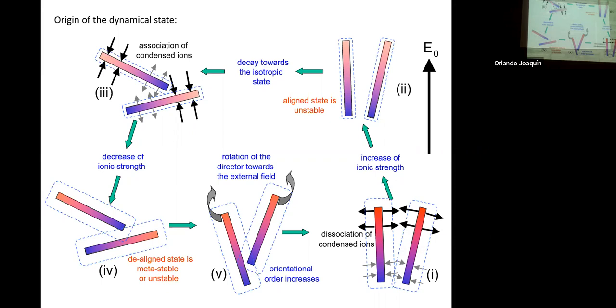But as soon as it becomes isotropic, you have a reassociation of the ions, and the rod will approximately attain the original state. That is to say, the ions associate, the ionic strength decreases, and that increases the thickness of the electric double layer, giving rise to an increase in the effective concentration and making the aligned state unstable.